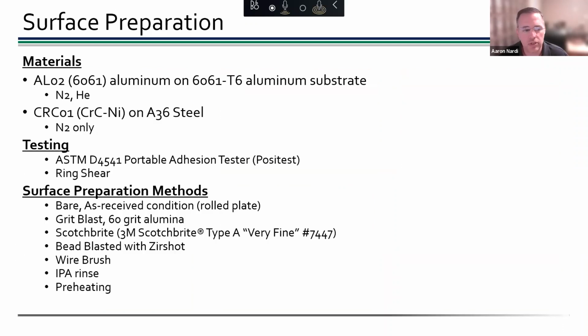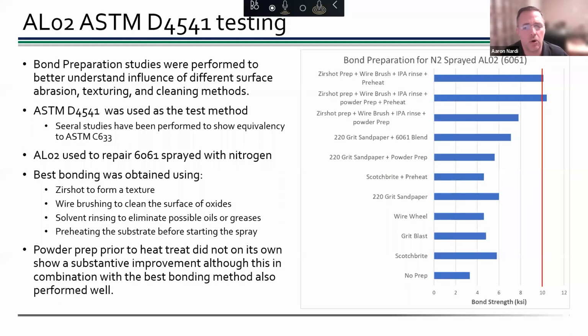Did some surface preparation studies. I'll skip past the words here and get to the meat of it. So this was work we did with our ALO2 material, which is a 6061 variant material. And what you can see here is this is all very similar to ASTM C633. It's the D4541, which is that like POSI tester, right? It's a portable adhesion tester. And we get pretty good correlation between the two.